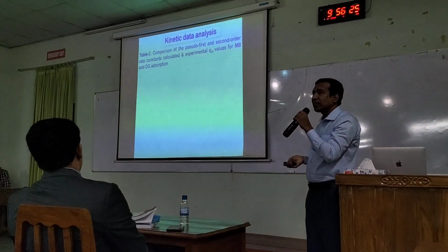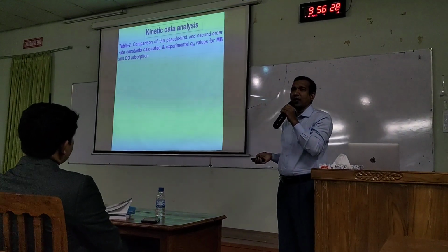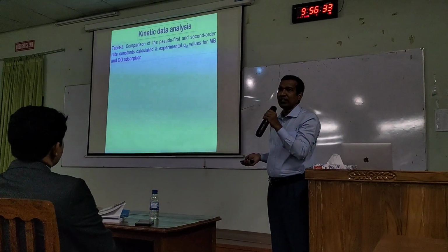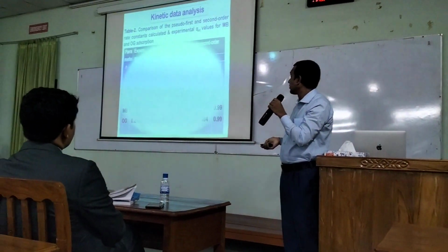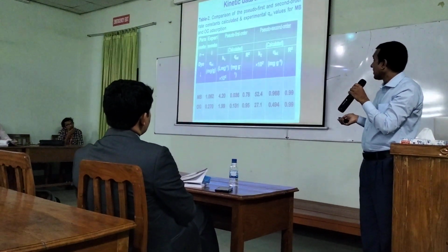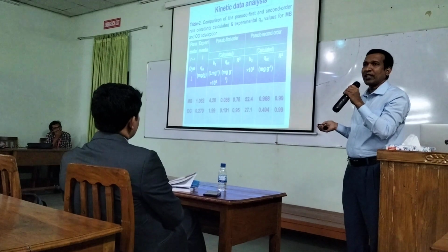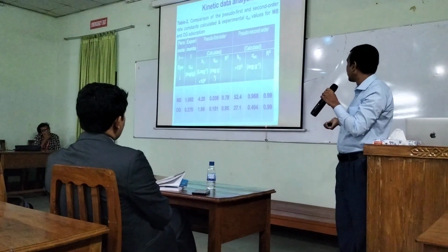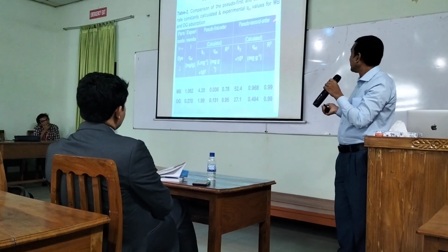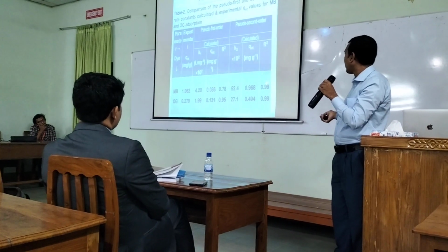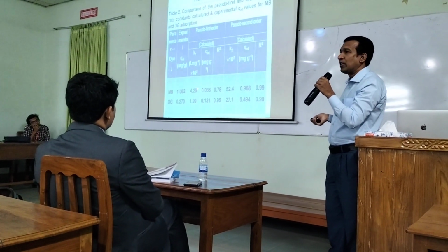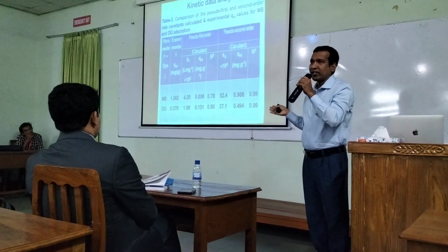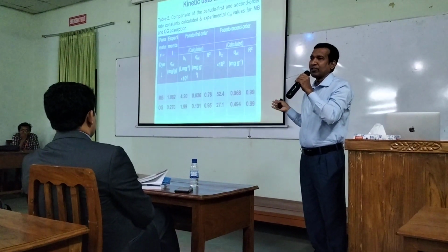And to understand the mechanism of dye adsorption, we studied adsorption kinetic models and adsorption isotherm models. Here I have shown the results for the pseudo-first order and pseudo-second order models. From these calculations, we clearly see that the regression coefficient for pseudo-second order is much higher than pseudo-first order, which means that our data potentially describe the pseudo-second order model.